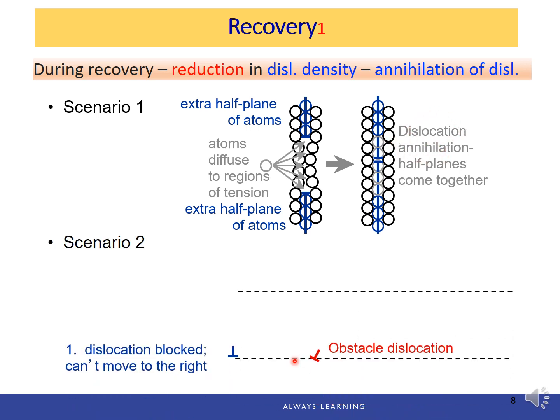Second scenario, the reduction in the ductility is because the dislocation motion is impeded. So here's one example. If we have a dislocation in another orientation, this dislocation in red becomes the obstacle for the blue dislocation to move. Therefore, the material is stronger or less ductile because the dislocation motion is blocked, and cannot move to the right.